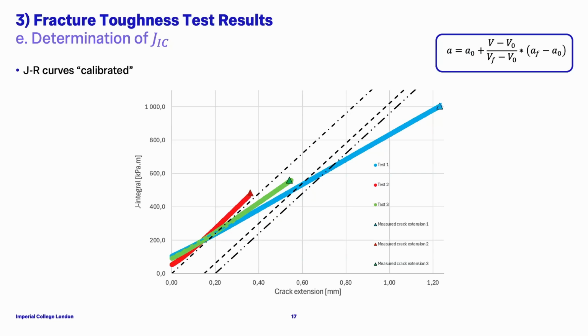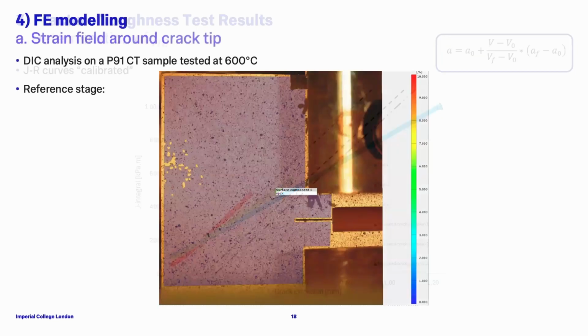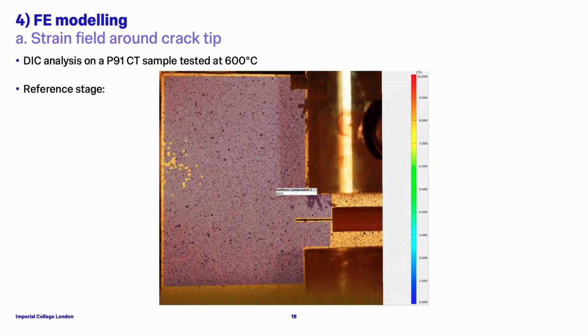So for me, what can explain these curves is, as I mentioned, the two phenomena we saw physically. That is to say, the huge contraction effect on the sample, and also the tunneling effect, because the standards assume that the crack extension will propagate as a straight line, but we saw that it was more of a tunneling effect, more of a parabolic shape. And so these two main issues might explain the difference between the actual physically measured crack length and the predicted one.